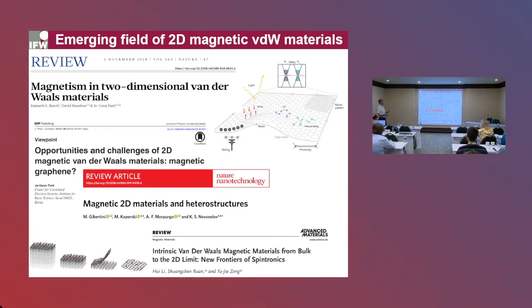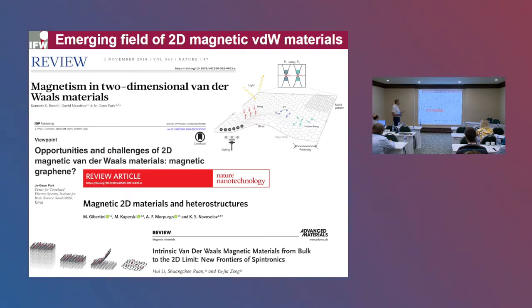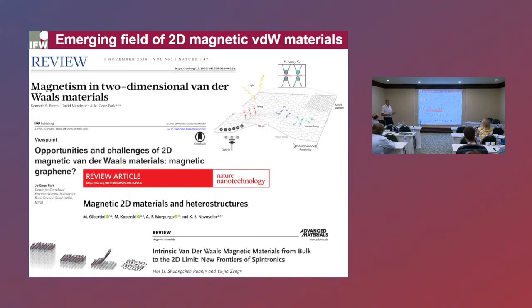The reason for this renewed interest is that these are van der Waals materials — they are easily cleavable, and one can with relatively little effort achieve single or few-layer two-dimensional magnetic systems, which is very flexible in terms of changing their properties. For instance, depending on the chemical composition or external stimuli like strain or pressure, one can change the spin Hamiltonian from a truly isotropic Heisenberg form to an Ising or XY one. One can also think of doping these two-dimensional layers by electrical gating, providing a range of potentially interesting functionalities.